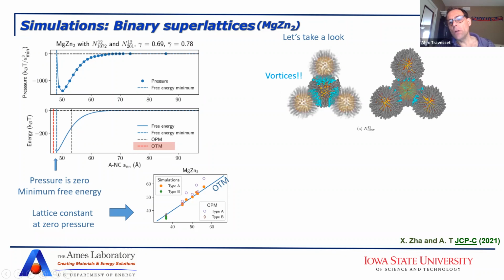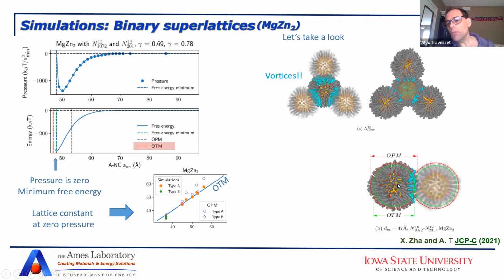In both cases, you can even look a little more closely, and you can take these things and then put here the OPM. The OPM is the hard sphere diameter, and you can see how the hard sphere diameter overlaps. And this is extremely well described by the OTM. Here you have the OTM. So you see how the distance between these two particles follows the OTM.